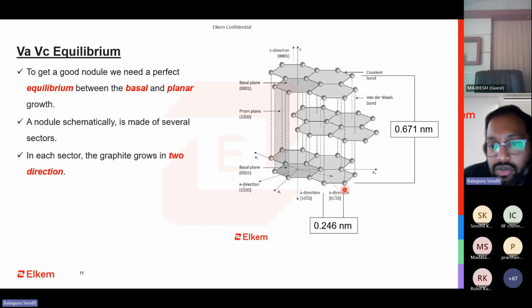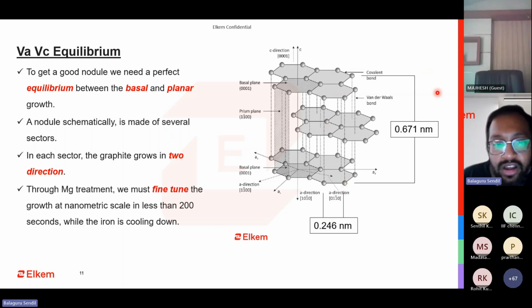But for forming a nice nodule, we need both of these to grow at a correct rate. You need to have an equilibrium. You don't want to completely eliminate this growth. This also needs to grow. So that is why an equilibrium between both these basal and planar growth needs to be achieved. So that is why your FSM, what you are adding, should be very critical. Each nodule that you produce undergoes a lot of logic.